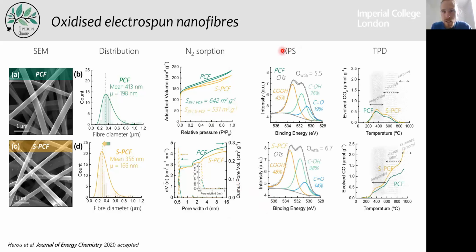And if we look at the XPS, we can see that we have slightly higher oxygen content here in the stabilized sample. And if we do some TPD, that basically investigates the amount of acid groups by the evolution of CO2, or the amount of basic groups by the evolution of CO, we can see that the acidic groups are fairly similar, whereas the stabilized sample has many more basic groups, particularly ketones and carbonyls, which have been shown to be particularly efficient for pseudo-capacitive storage.